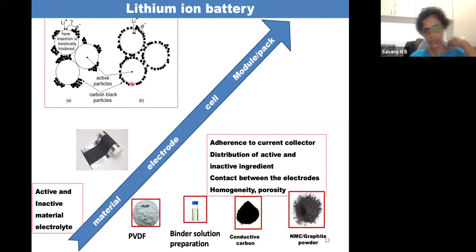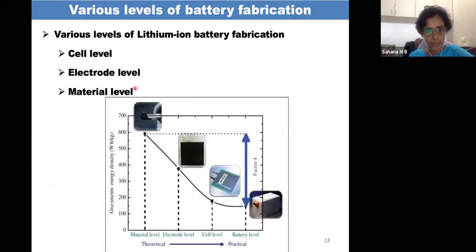So this is our starting material, down here on the left side. From this we need to prepare the electrode. The various levels of lithium ion battery fabrication are, first the material level, then the electrode level, and then the cell level. Now if you can see here, this electrode will have a very good theoretical capacity or energy density of 600 to 700 watt hour per kg. That's if you take only the active material, its theoretical or intrinsic capacity or energy is very high.